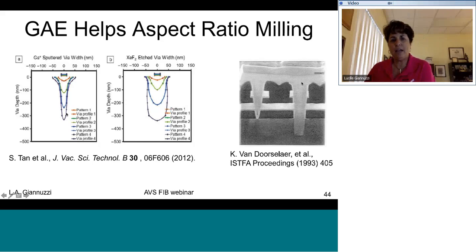If you incorporate now a gas, which will enhance the sputter yield, basically this helps to pull the sputtered material out of the trench so that you don't get redeposition. You can actually FIB mill deeper and reduce the V-shaping, which is limited by the redeposition of the sputtered material. Okay, so the enhanced etching increases the sputter yield by interacting with the material, making it volatile, and pulling it out of the trench. All right.